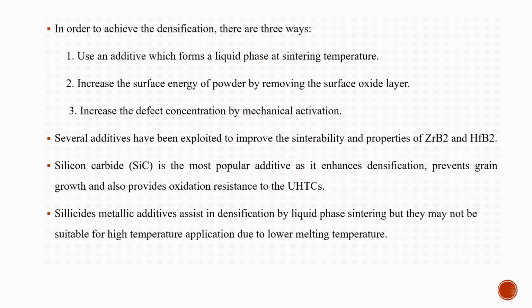In order to achieve the densification, there are 3 ways. 1. Use an additive which forms a liquid phase at sintering temperature. 2. Increase the surface energy of powder by removing the surface oxide layer. 3. Increase the defect concentration by mechanical activation.